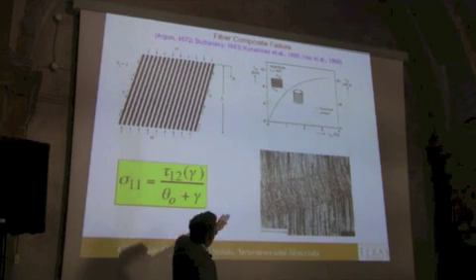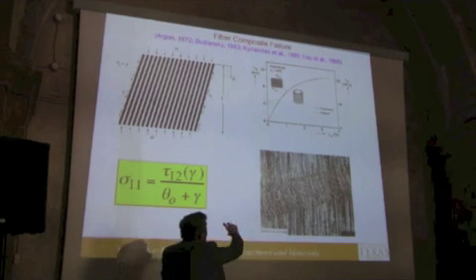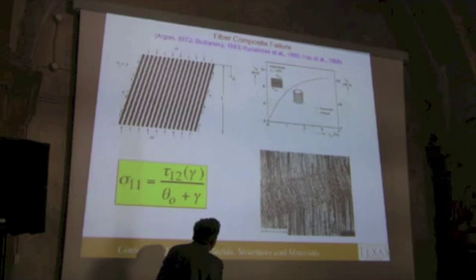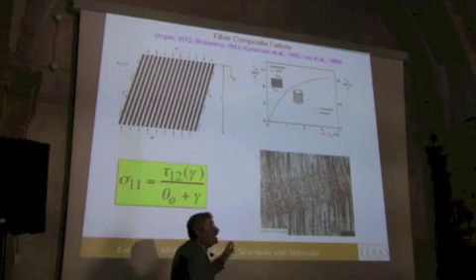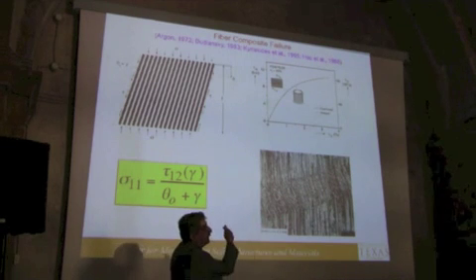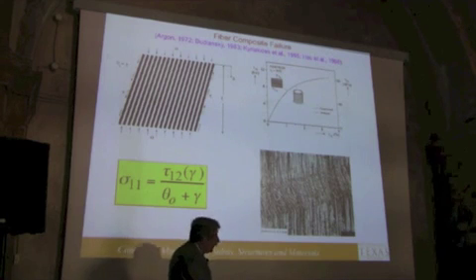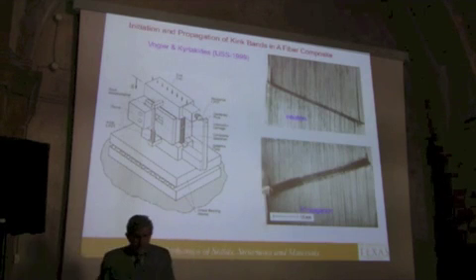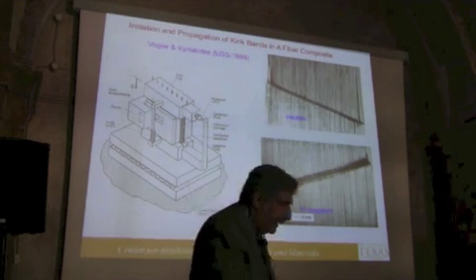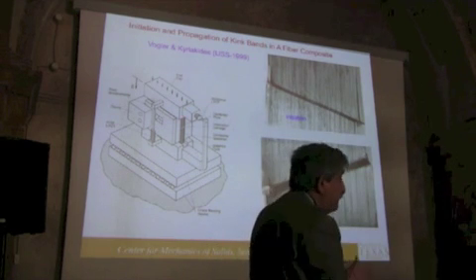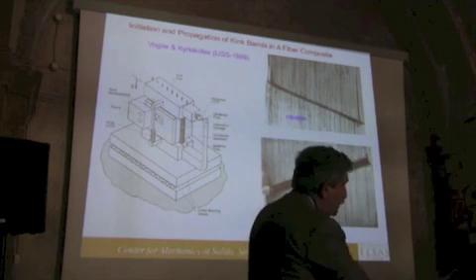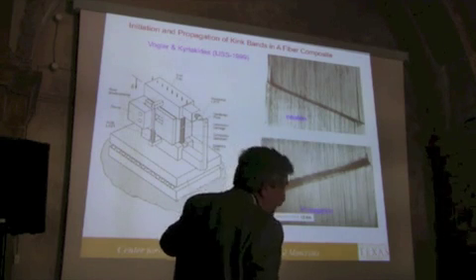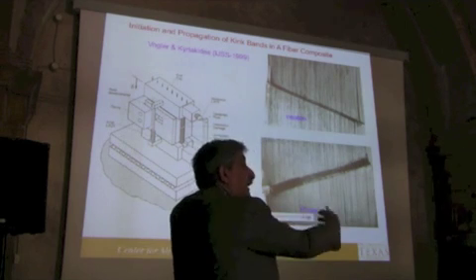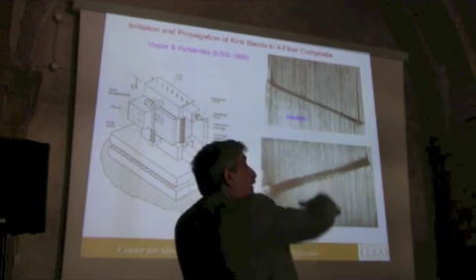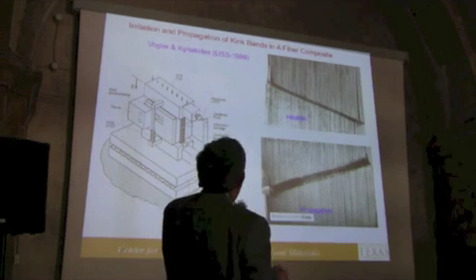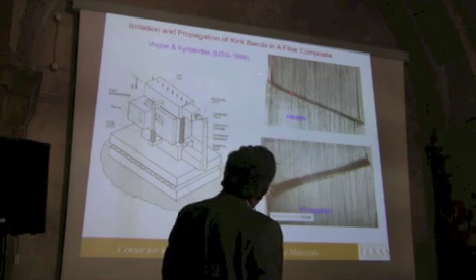That's really what's behind the onset of failure, and the fibers bend locally, and once they reach a certain amount of curvature, they break, and this is a clean kink band. This breaking that occurs, in a minute you will see why, is a catastrophic failure. If it's totally uniaxial, and you just compress it in a simple way, it just simply blows up. But if you constrain it, let us say that it's a laminated composite, and it has protection on either side of fibers that are not in the zero direction, and they can take more load. If you do that, then it will fail, and it will develop a kink band like you see here.